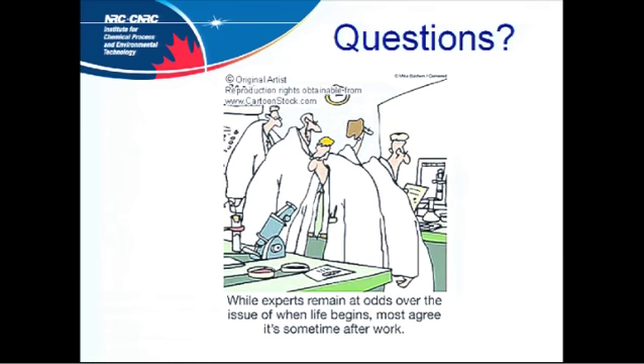It depends. The problem with laboratory instrumentation is that it depends a little bit on the sample and everything else. One of my favourite setups, although it's very uncommon, is one with twin mirrors. It's a very odd one because you end up having two sets of mirror optics, so it's quite expensive. But you tend to get the advantage from the parallel beam side of also getting some focusing, so you get a reasonable resolution as well. There is a downside to that, which I can explain to you later. But as ever, laboratory instrumentation is always a compromise. You gain on one hand by doing something, but you lose on something else.